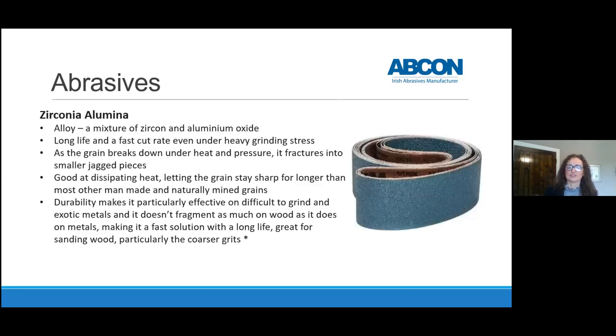Zirconia alumina. So zirconia is an alloy, a mixture of zircon and aluminium oxide. It has a long life and a fast cut rate, even under heavy grinding stress. As the grain breaks down under heat and pressure, it fractures into smaller jagged pieces. So it's good at dissipating heat, letting the grain stay sharp for longer than most other man-made and naturally mined grains. So its durability makes it particularly effective on difficult to grind and exotic metals, and it doesn't fragment as much on wood as it does on metals, making it a fast solution with a long life, great for sanding wood, particularly in the coarser grits.